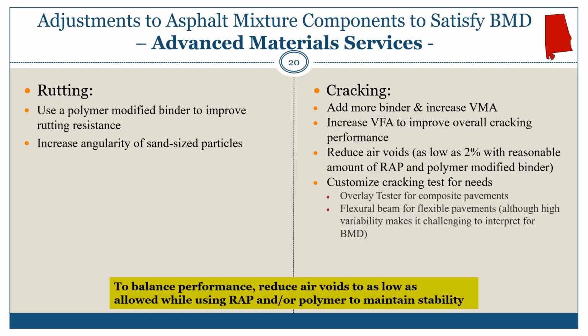Brian Prowl at Advanced Materials Services. What Brian recommended is that if you wanted to improve your rutting, use a polymer modified binder. Very quick and easy way to do that. Increase your angularity of your sand-sized particles, your aggregates passing the number 4. So having something with a higher fine aggregate angularity or uncompacted voids will help improve your rutting performance.